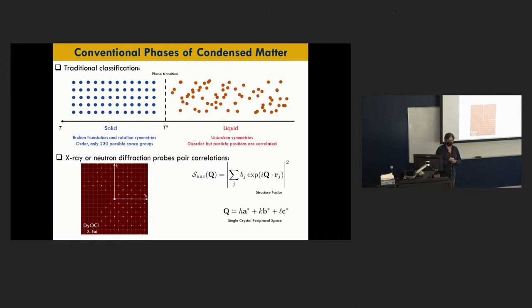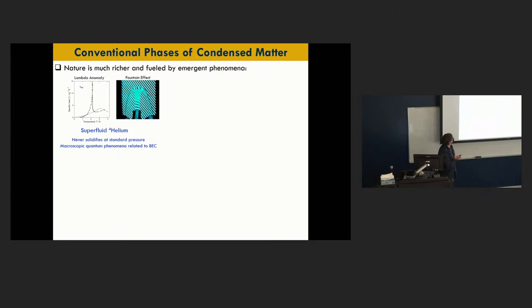But one thing that you may not be aware of is that there are certain materials that do not fall into this classification of solids and liquids. And one example that physicists like to talk about is liquid helium. So when you cool liquid helium to low temperatures, it actually does not freeze. And at some temperature of the order of 2 Kelvin here, you have a phase transition between two phases of the liquid. And this phase transition characterizes the emergence of a macroscopic quantum phenomenon that we call superfluidity.